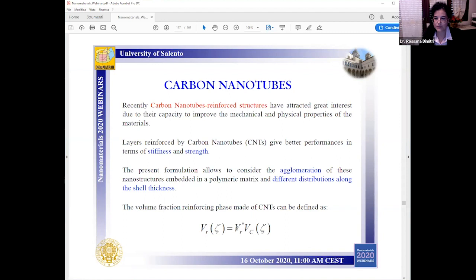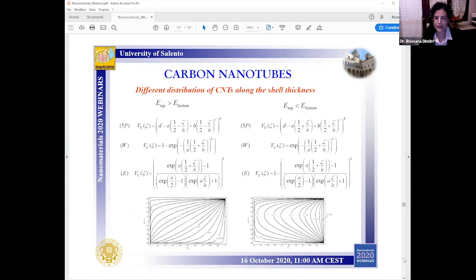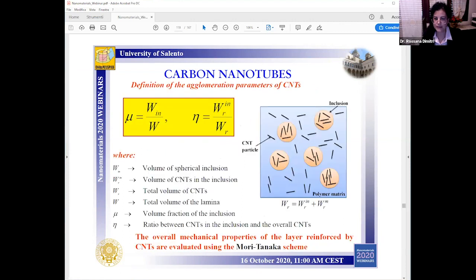by means of this quantity VR, which is the carbon nanotube volume fraction value that depends on the carbon nanotube mass fraction and density of both the matrix and the reinforcing phase. And VC instead is defined by different distribution laws throughout the thickness, as reported here in this slide. So the overall mechanical properties of the layer reinforced by carbon nanotubes are evaluated using the Mori-Tanaka scheme.